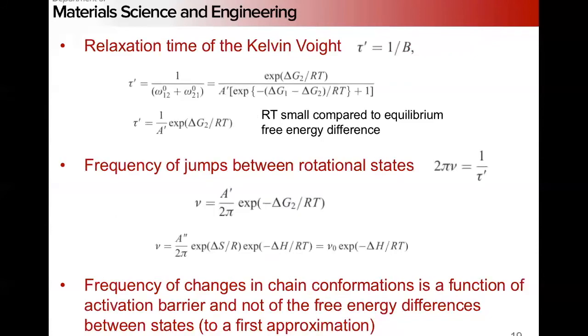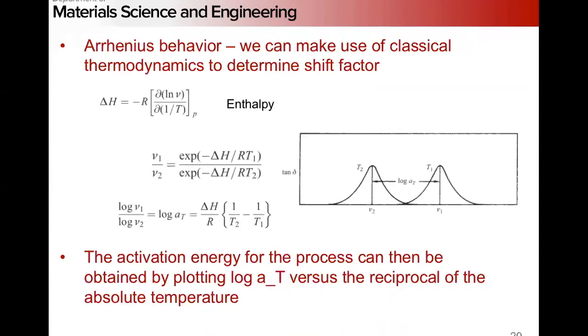We have here a change in enthalpy. Our frequency of jumps between these states is related to an enthalpy term. We know how to relate enthalpy to the frequency and temperature, so we can think about our changes in frequency at two different temperatures and extract the shift parameter. And once we have our shift factor, we can relate the activation energy for the process by plotting the log of our shift factor versus the reciprocal of temperature. That will give us our activation energy for the chain relaxation processes of interest.